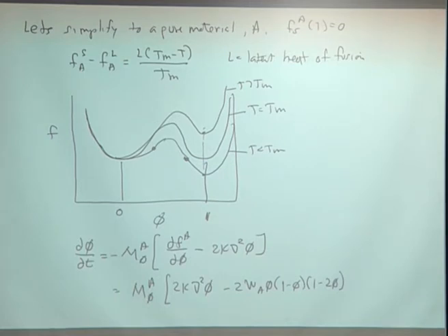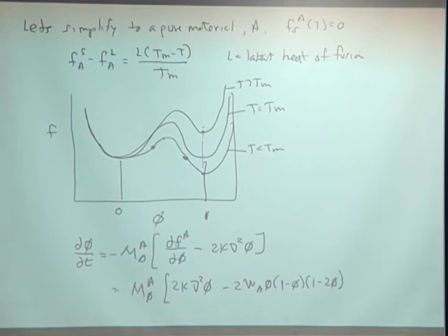And so you're throwing out a lot of the physics. What you have to hope is that when you actually run this model as a computational tool, you don't get anywhere near those spinodals, because bad things will happen. And so it's a computational engine. It's not a physical model. So again, you've picked up on exactly the essence of what this is.